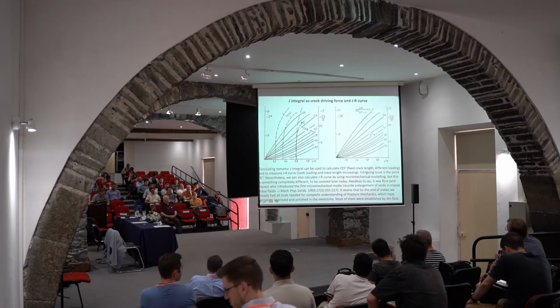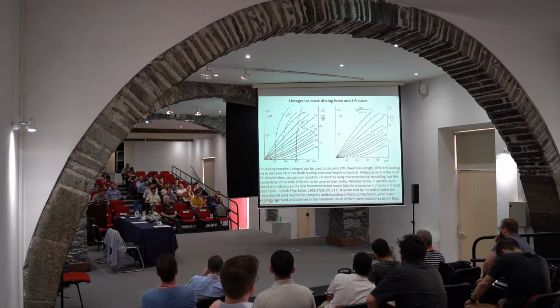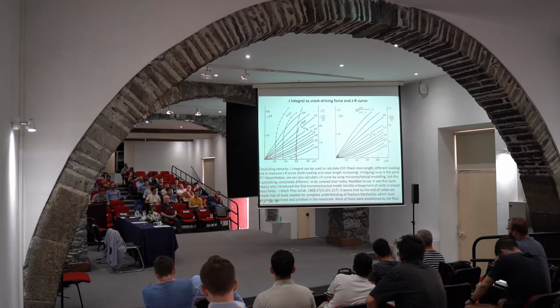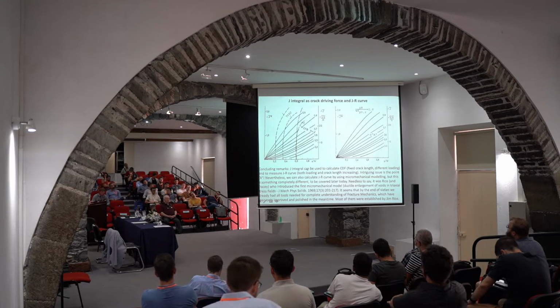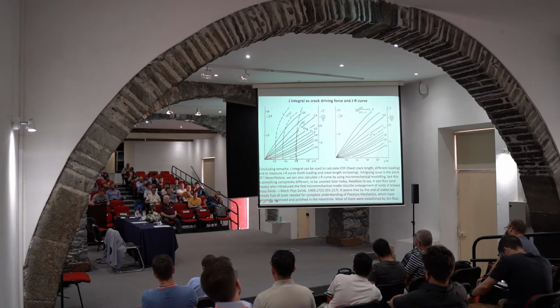In this case, it is defined as approximately 0.83, I would say, which is just a parameter indicating critical pressure. It is about 83% of pressure that would correspond to yield strength. So I would say it's a surprisingly high value. We are dealing with 60% of crack depth. We are analyzing the problem of crack growth through the thickness. And in some other cases, it's even higher.